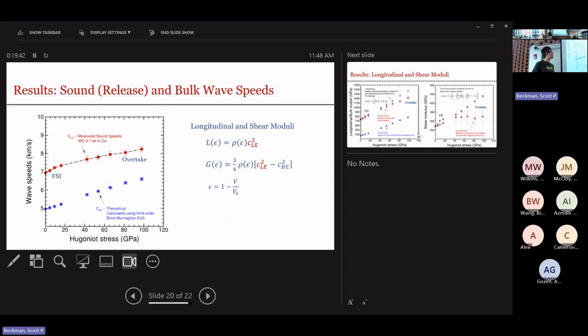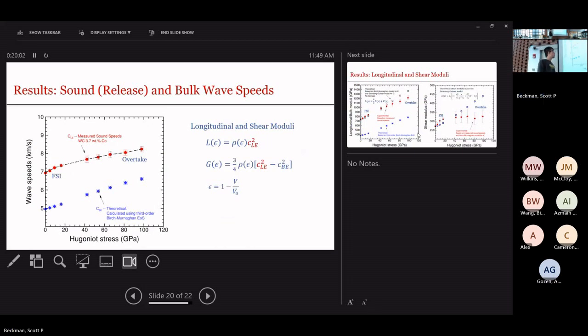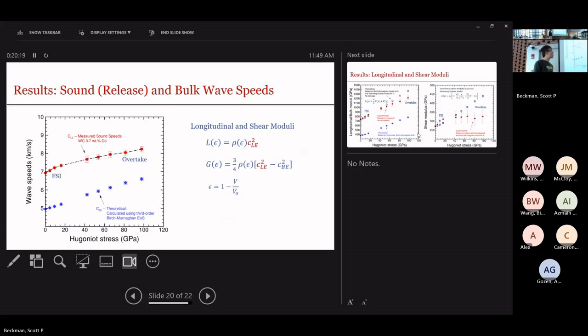The results show the measured sound speed at different shock stresses — red symbols correspond to experimentally measured longitudinal sound speed, and blue symbols correspond to the theoretical bulk sound speed obtained using a third-order Birch-Murnaghan equation of state. From these two quantities we can calculate both the longitudinal modulus and the shear modulus.